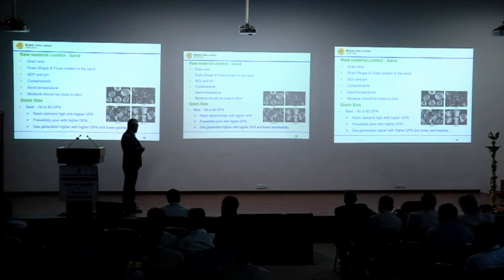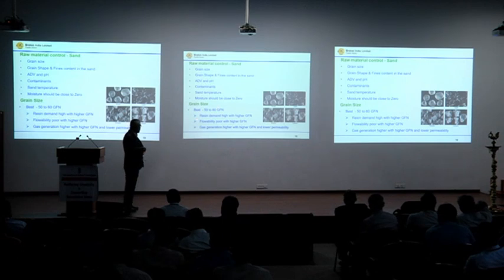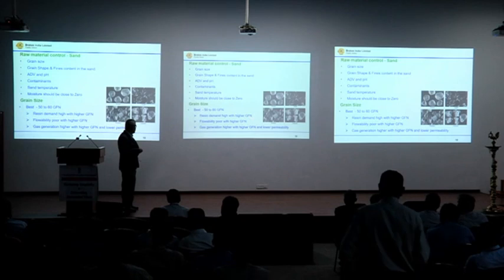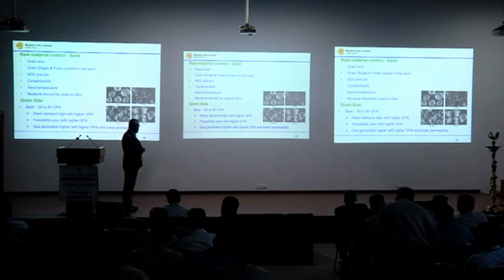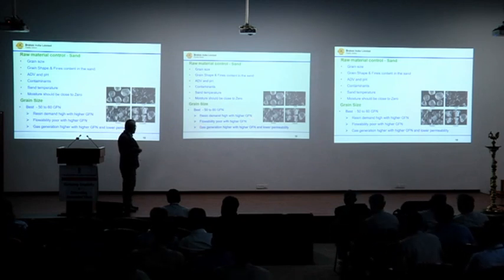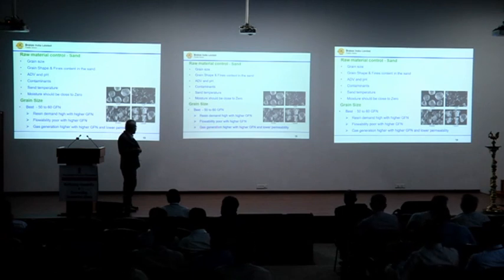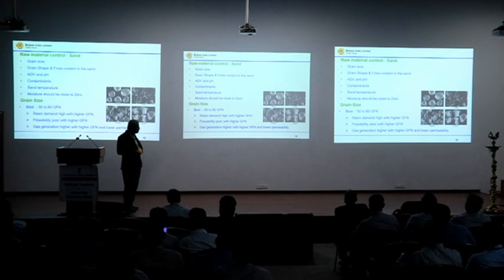The grain size of the sand, 50 to 60 AFS, is best suited. Resin demand is higher with higher GFN number. Flowability will be poor with higher GFN number. Gas generation is higher with higher GFN, and permeability is lower.